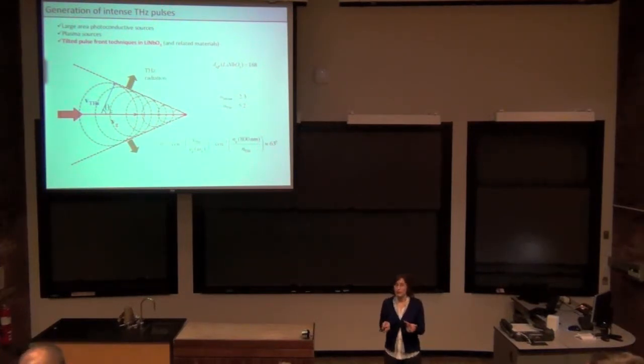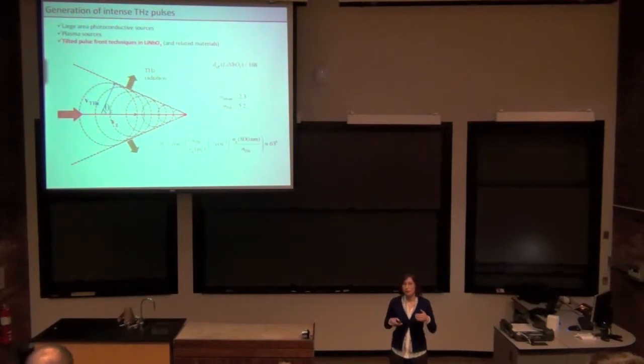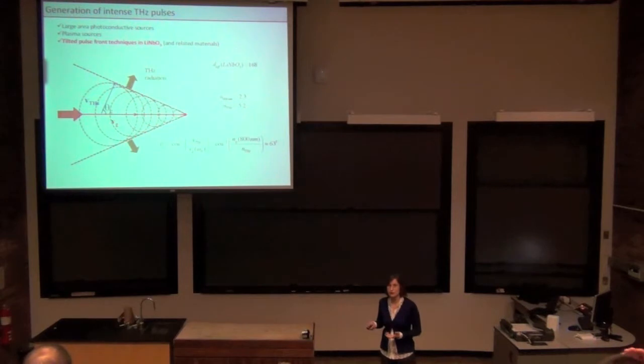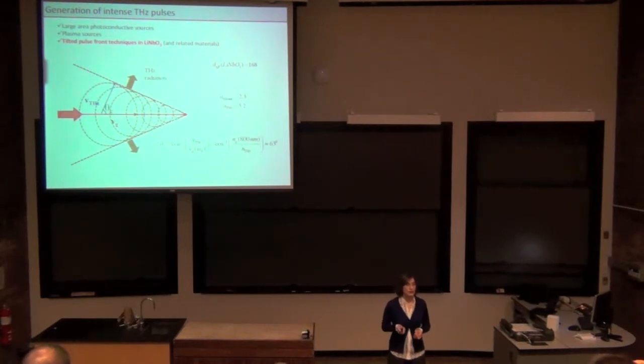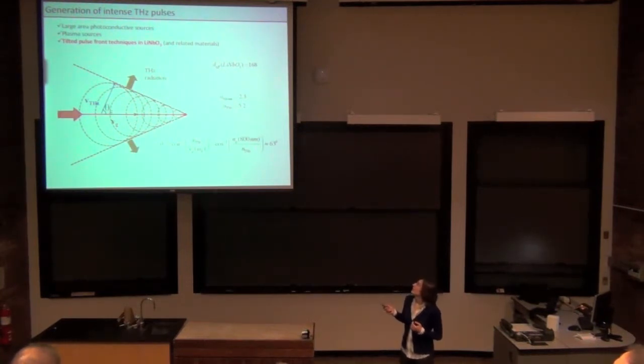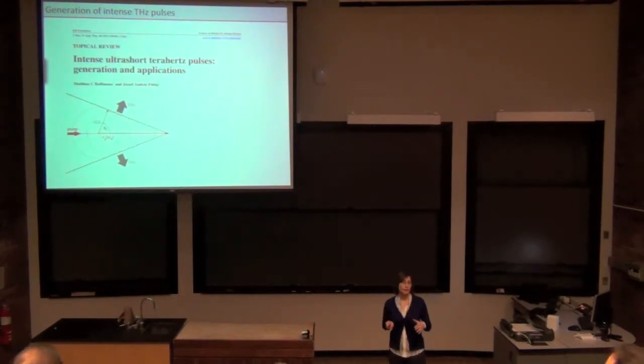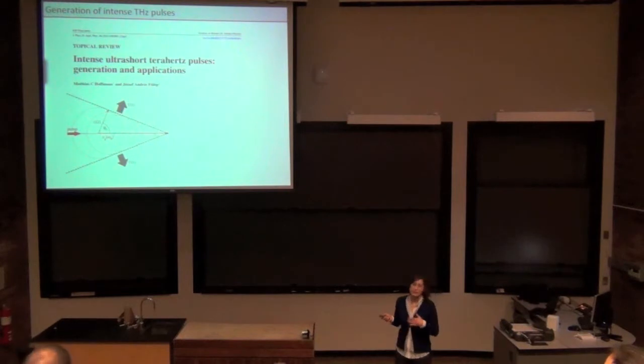They do not propagate together, so their transfer of excitation from the optical wave to a terahertz wave is inefficient. This cone actually happens to have this angle of about 63 degrees. About 10 years ago, Hebling and collaborators proposed a very elegant way to overcome this problem, and that is by tilting the pulse front of the excitation beam.